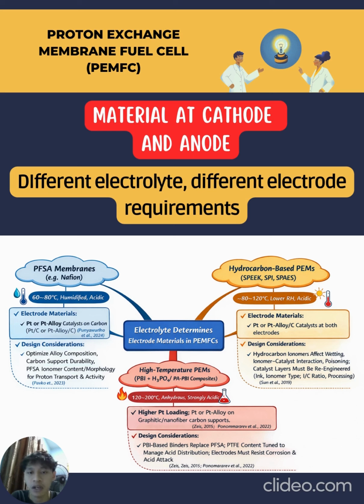Additionally, with this kind of electrolyte, PBI-based binders are employed instead of PFSA ionomers, and PTFE content is carefully tuned to manage acid distribution and maintain electrode integrity over long-term operation.